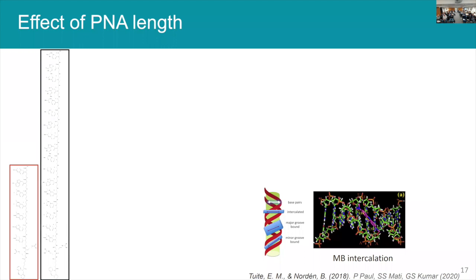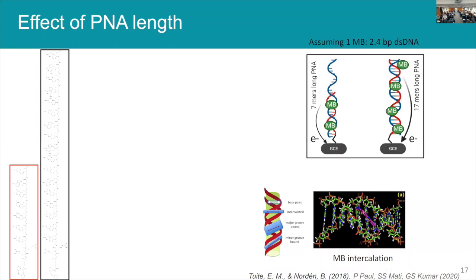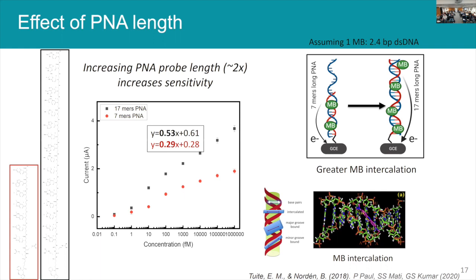And so also some people are saying that it's around, let's say, 1 methylene blue per 2.4 base pairs. So our hope is if we're going from this 7-mer base pair duplex here towards 17-mer, we should at least see a times 2.4 increase in the signal because of the 2 times more methylene blues that can fit in between the duplexes. So hopefully we see that, and that's exactly what we saw.